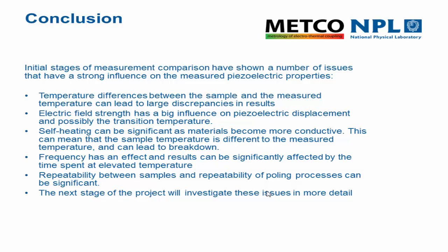So in conclusion, temperature differences between the sample and the thermometer that you're using to take the measurement need to be carefully considered and validated. Electric field strength can have a significant effect on both the electric displacement but also on the effective transition temperature. Self-heating is a significant issue as samples become more conductive at higher temperatures, and the measurement frequency and the timing of the test can have a big effect as well.